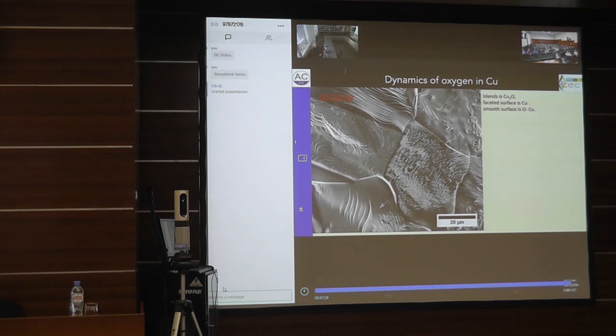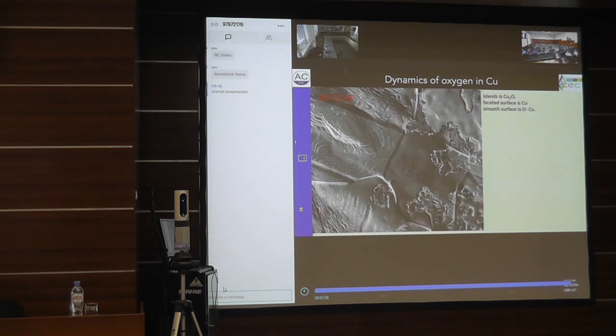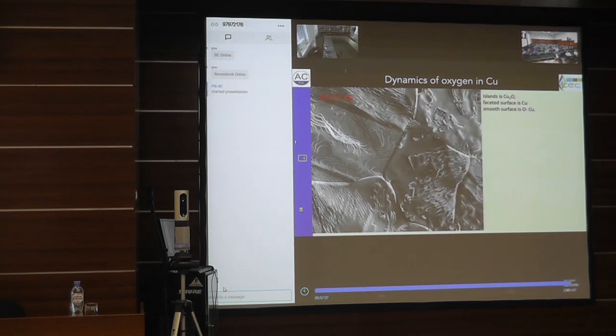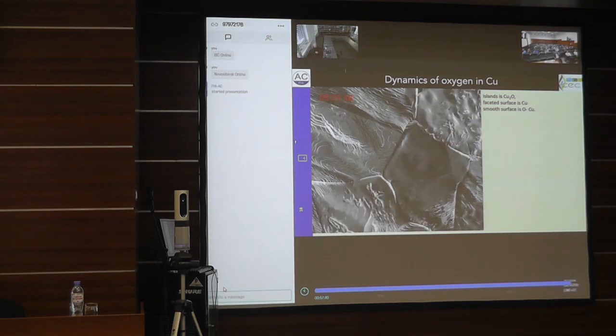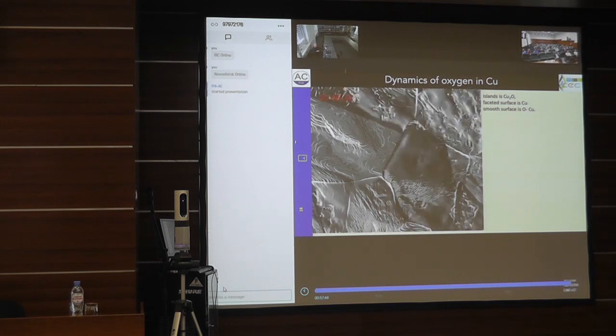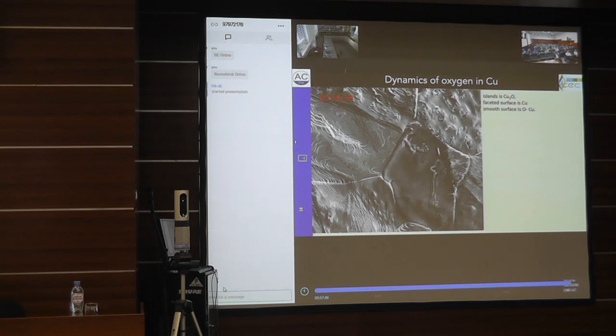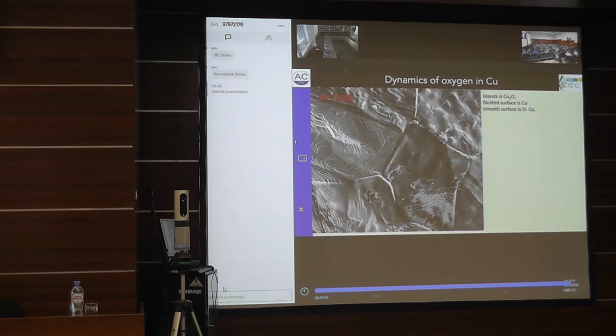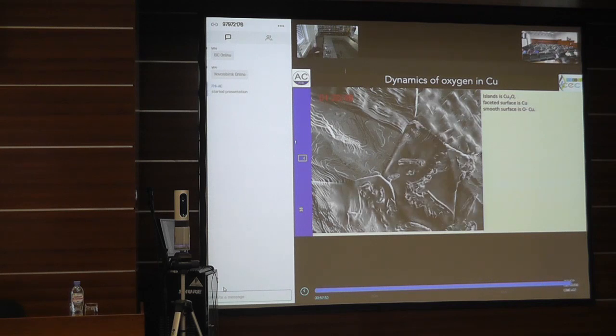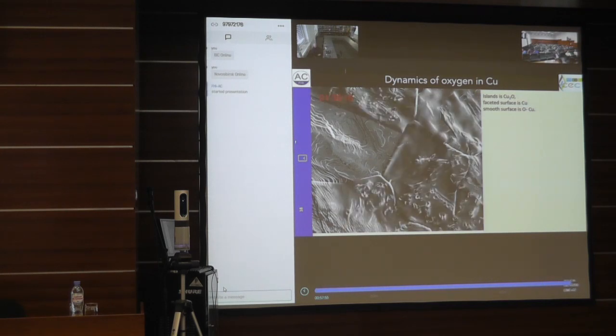And now we put this into a temporal evolution under reaction conditions that are typical for methanol synthesis, and then you see a clock, and then you can observe what the surface does. So it is truly dynamical, and you see that the interface is completely changing backward and forward, and this reaction is driven by an oscillatory process between copper oxide and copper plus oxygen. And that explains, of course, why the zinc oxide can never be fixed on the surface, because if the surface itself is moving that way, then the zinc oxide will, of course, always be shaking around.